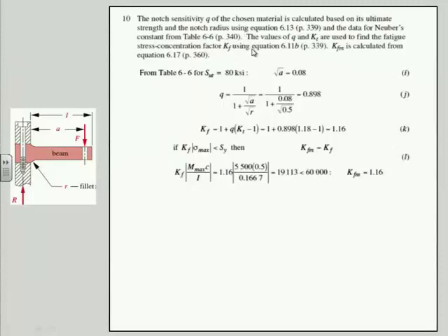So I go to the tables, the so-called Neuber factors, right here, table 6.6. And these page numbers are third edition numbers, so it's going to be a little bit higher in your fourth edition, probably 4 or 5 pages later. So I go into his table for a material with an SUT of 80,000 psi, which is this particular material, and he tells me the square root of A is 0.08, and I use that and the R of the notch, the radius of the notch, to calculate a Q factor of roughly 90%.